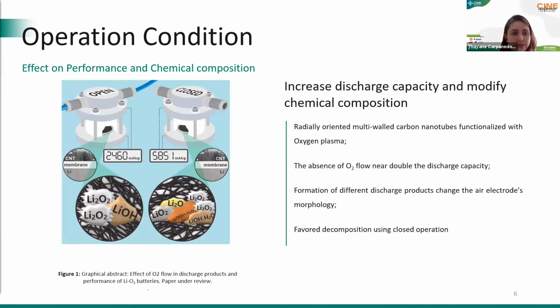Here are the first results that I'm going to present, using radially oriented multi-walled carbon nanotubes produced by the chemical vapor deposition method and functionalized with oxygen plasma. And we evaluate the influence of oxygen continuous feed during the battery operation. Here we have the two possibilities of operation that we studied: the open one, where we have the flow during all the performance tests, and the closed, when we have the feed in the beginning, and then during the performance test, we have a completely closed system.